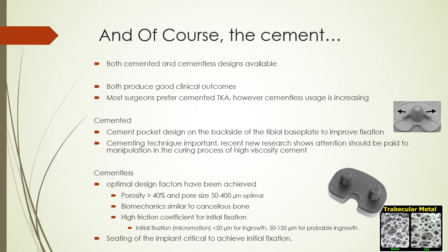Cementing technique is important. And in the recent few years, we have actually even noticed that the selection of the cement type is also important. There are studies published on using high viscosity cement during the surgery. While the cement is setting, we are not supposed to manipulate the knee too much, as it may contaminate the cementing surfaces that later leads to less fixation. So when you are dealing with high viscosity cement, make sure you pay attention to not manipulate too much during the curing process.